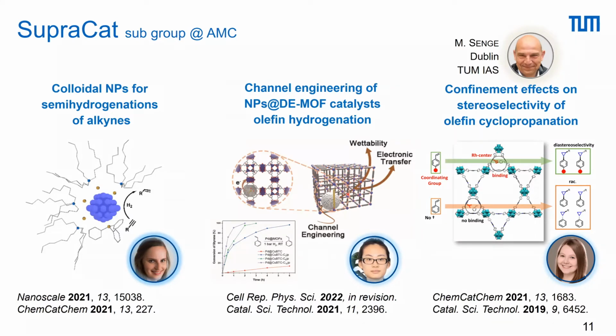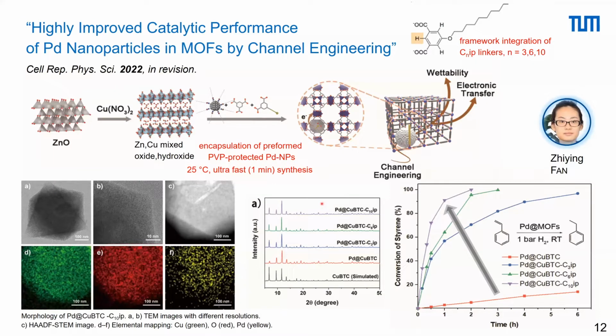I can show you here the effects you can integrate into these heterogeneous hybrid systems by defect engineering of MOF materials. So what Zhiying was doing, she developed an ultra-fast, one-minute, very smooth, ambient condition synthesis of the whole MOF, by a clever choice of precursors. Why is this important? Because if you have long reaction times or high temperature, which is usually the case in MOF synthesis, then you would aggregate your nanoparticles. So if you want to keep preformed palladium nanoparticles stable in terms of size distribution, then you need this ultra-fast,